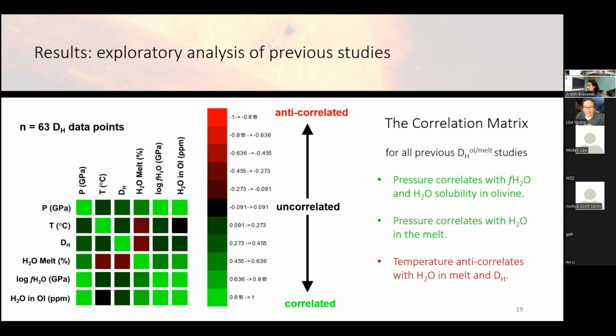I also want to note for these experiments that it's kind of difficult to decouple the pressure and temperature variable, which is why you do see a weak correlation there. And that's simply because if you're synthesizing crystals, you do have to be in a somewhat narrow pressure and temperature range. It isn't possible to do this at any given arbitrary temperature and any given arbitrary pressure. So that's another complicating factor for how to run these experiments.